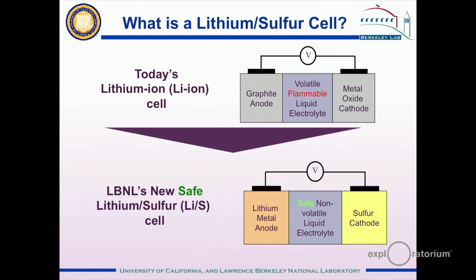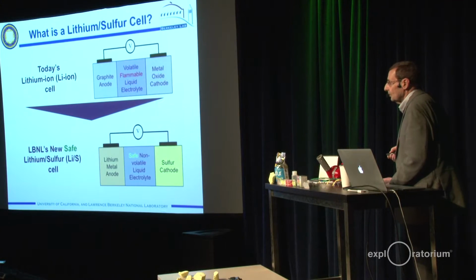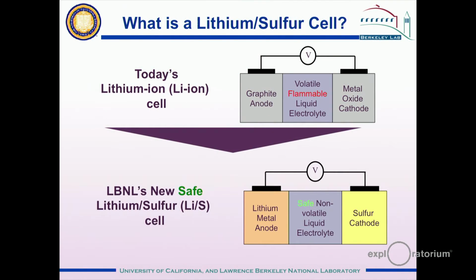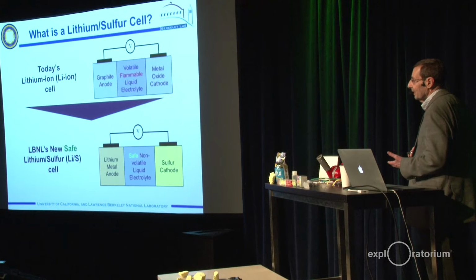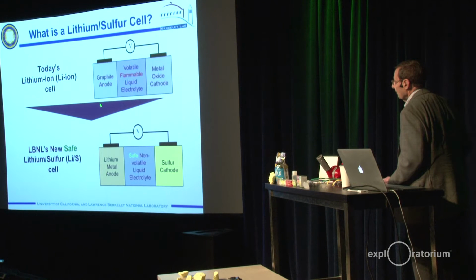Now, as we all know, the electrolytes that are used in lithium-ion cells are very flammable. And when you heat up the lithium-ion cell, the transition metal oxides release oxygen. So sealed inside the cell, we have all the makings of a fire. We have the oxygen from the transition metal oxide, and we have the organic flammable solvents in the electrolyte. So the fire can start inside the battery, and then the battery breaks open. It's not the reverse. The battery doesn't break, and then the fire starts. So in our work, we're making changes to all of these elements of the cell. Instead of having a graphite anode, we use pure lithium metal as a negative electrode.